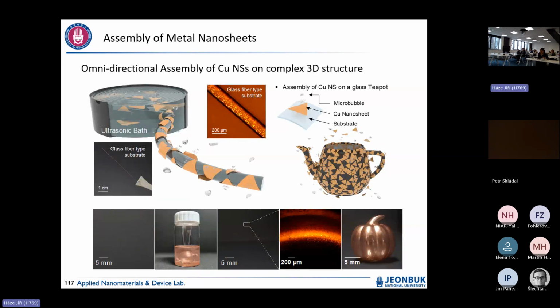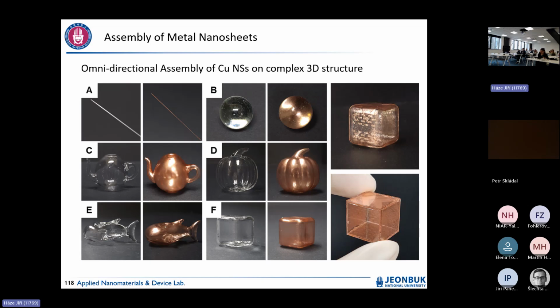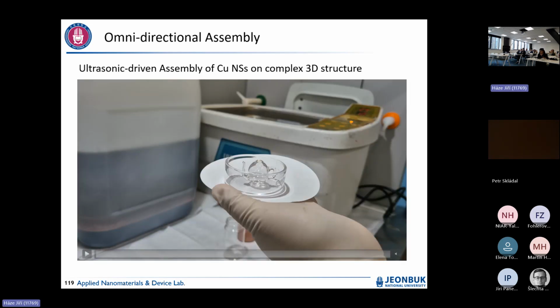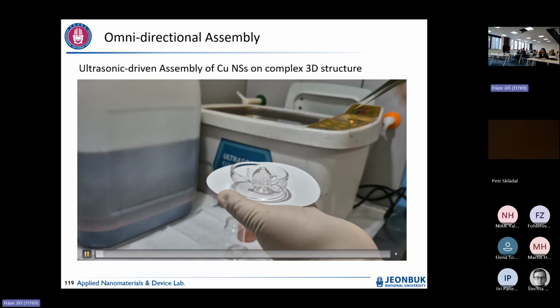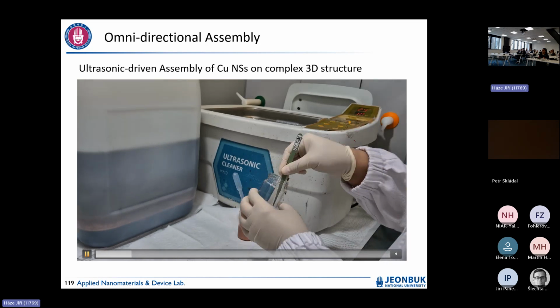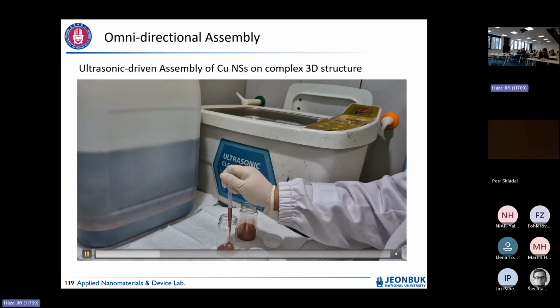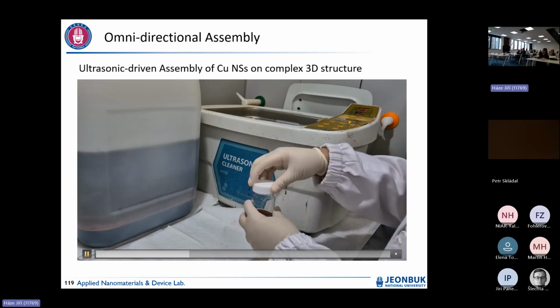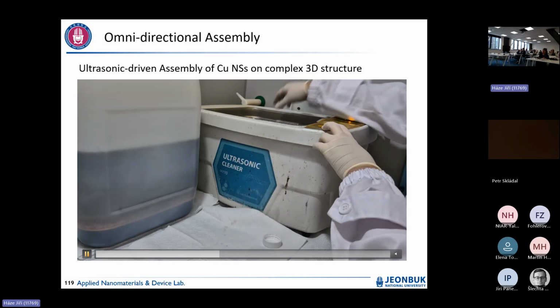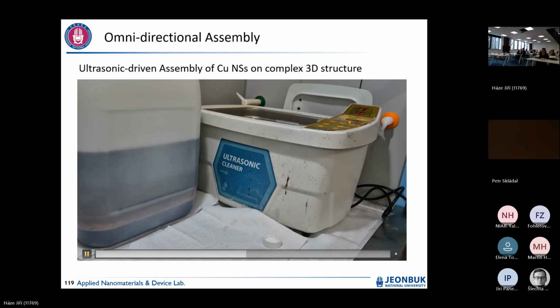Any complicated structure is possible because it is omnidirectional. When you put in a fiber, or a pumpkin, dolphin, glass, whatever you're thinking, you just press the button and can assemble copper nanosheet on the surface. This is very simple and very short. We use glass, and you can see here an ultrasonic cleaner. Then put a sample here, and it takes around 10 minutes, I guess.